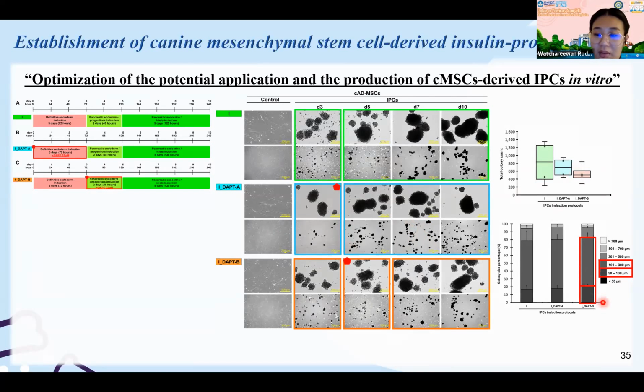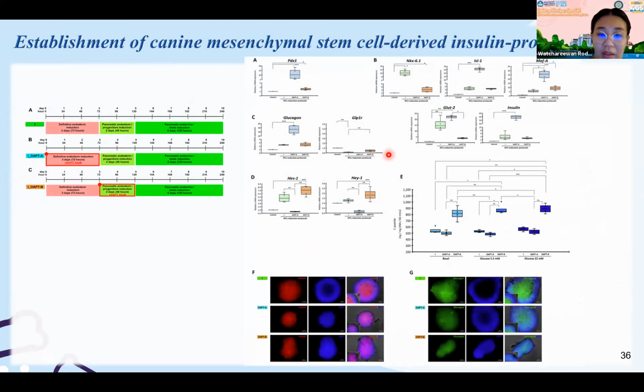we found that the size of the colony is mostly moderate and small, especially when we use the DAPT at the second step, which I'm going to call DAPT B. So how about the gene? As before, the DAPT B group here shows good production of the IPC in the small and the moderate size.